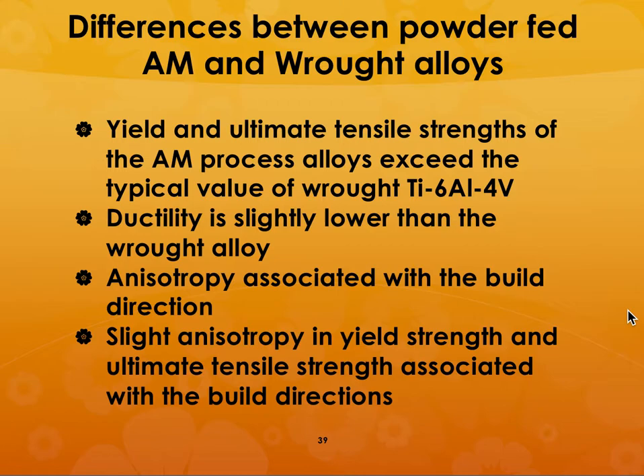So what are some of the differences in the powder fed systems and alloys that are made, as compared to wrought alloys? Yield and ultimate tensile strengths of AM process alloys, especially in the direction of the additive manufacturing process, far exceed the typical value for a wrought alloy, because wrought alloys are typically isotropic, whereas in the case of anisotropy, they are not the same.